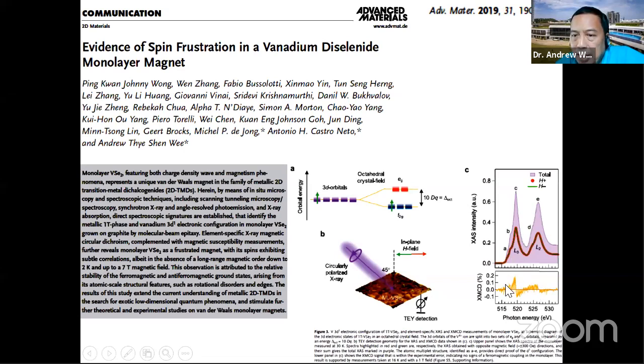You can see that the dichroic signal, that means the difference between the absorption peaks in different helicities, so clockwise minus anti-clockwise helicities, which you can get on a synchrotron, gives a signal which is less than 0.2%. So it's barely above noise. So we don't observe any significant magnetism in this system.